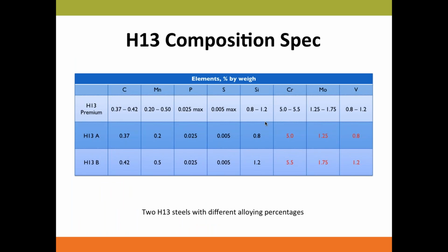Now we look at the specs of H13, the most commonly used steels. On the top row, you can see a premium grade H13, and we know from steel mills that the way they control the process gives us a window for specs. But you can see the most important alloys in the H13, which are chromium, molybdenum, and vanadium, the last three columns, they do give it kind of a leeway there. They are saying for chromium 5% and 5.5% is also within spec, and for molybdenum and vanadium as well. So you can have two H13s with two different alloy percentages or concentrations.